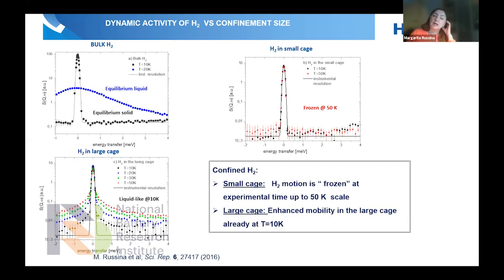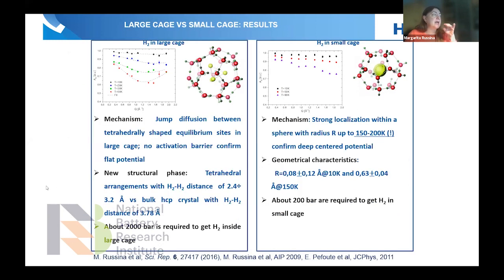So we see here that it is moving at 10 Kelvin, when the bulk hydrogen is frozen. You see completely different dynamic responses just from slightly increasing or decreasing the cage size. You either localize the hydrogen or delocalize the hydrogen. And this is exactly due to this landscape shape, which you can analyze by looking at this factor which describes the geometry of the motion.